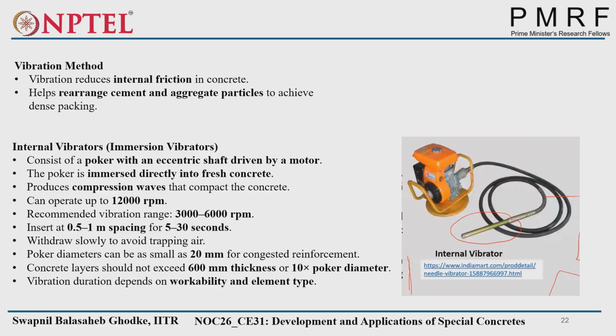Poker diameters can be as small as 20 mm, for congested reinforcement also. The concrete layer should not exceed 600 mm thickness or 10 times the poker diameter. This is the limit of the poker. Suppose you are using a 20 mm diameter poker: 10 times that is 200 mm thickness of slab you can vibrate with that poker. So 600 mm means you will require a 60 mm diameter poker for proper compaction. This is the upper limit for poker vibration. Other types of vibrators are available for higher thicknesses, as we'll see. Vibration depends on the workability and the element type, right?